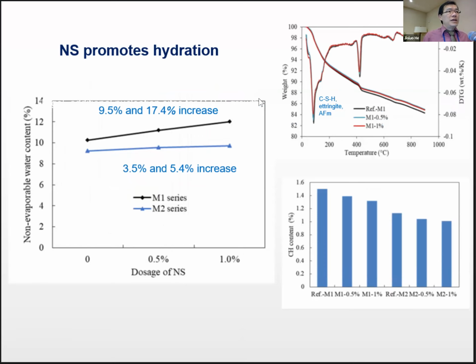One thing we found, which is kind of consistent with our understanding, is the nanosilica helped promote the hydration of the cement particles. If you see the left-hand side, as you increase the dosage of nanosilica from 0% to 1% by weight of cement, or weight of binder, I should say, then your non-evaporable water content increases. That's basically the bound water, which is an indicator of the degree of hydration or degree of polymerization of the CSH gel. But you will see also with the M1 series, which has less ash, you're seeing more increase, but with a lot more fly ash, the high volume fly ash binder, you're seeing less because there's not enough portlandite to react with the nanosilica.